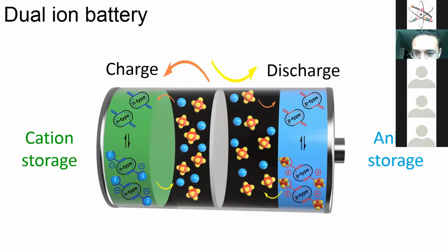So the working principle is different from the previous one. And for this, you need a large amount of the electrolyte, because by doing this, you will change the concentration of the salt in the solvent. And if you do this, you will change the ionic conductivity, and then the battery performance will be worse. So that's why it requires a large amount of electrolyte. So what is the important thing with this dual ion battery is the high voltage. Why? Because we can reach voltages between 2 and 3.5, thanks to the high potential of the cathode material based on a P-type material that can store anions.